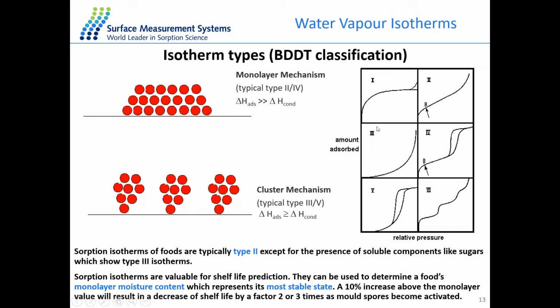And in case of some of the water molecules, they will have strong interaction with the water molecule itself, so it will form some cluster on the surface. And this kind of mechanism will result in the type 3 and type 5 isotherm. And it's not good for the BET calculation. And type 2 isotherm is considered as the most stable state of the probe molecule on the surface, and is quite important for the sample characterization.